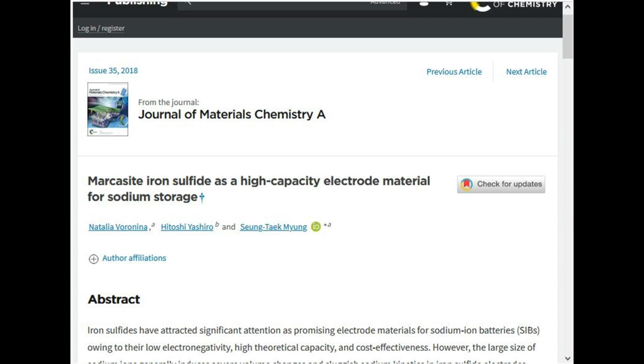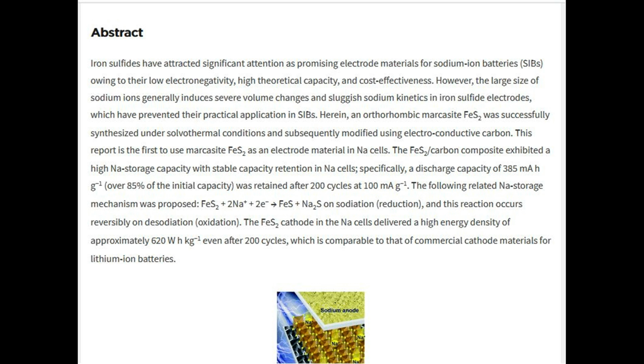Abstract. Iron sulfides have attracted significant attention as promising electrode materials for sodium-ion batteries, SIBs, owing to their low electronegativity, high theoretical capacity, and cost-effectiveness. However, the large size of sodium ions generally induces severe volume changes and sluggish sodium kinetics in iron sulfide electrodes, which have prevented their practical application in SIBs. Herein, an orthorhombic marcasite FeS2 was successfully synthesized under solvothermal conditions and subsequently modified using electroconductive carbon. This report is the first to use marcasite FeS2 as an electrode material in Na cells.